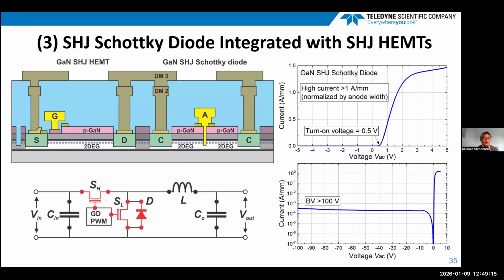The Schottky diode built in the same super heterojunction HEMT epitaxial structure is also very important because we will need the diode structure, especially in the low-side switch in DC-DC converter applications. Here I show the obtained IV characteristics in the linear and the log scale. The device shows a turn-on voltage of 0.5 volt, and a breakdown voltage of over 100 volt was obtained.